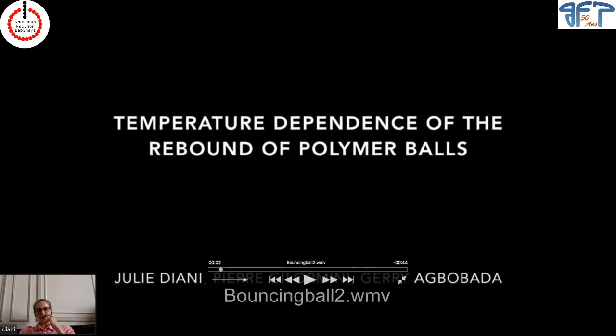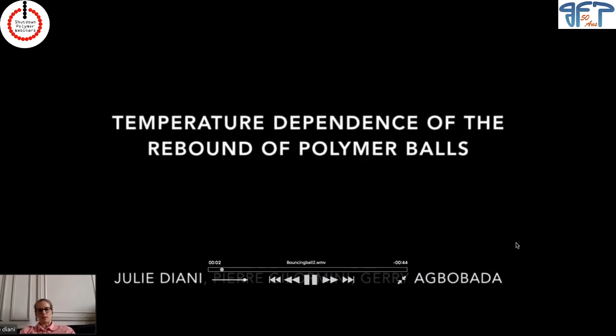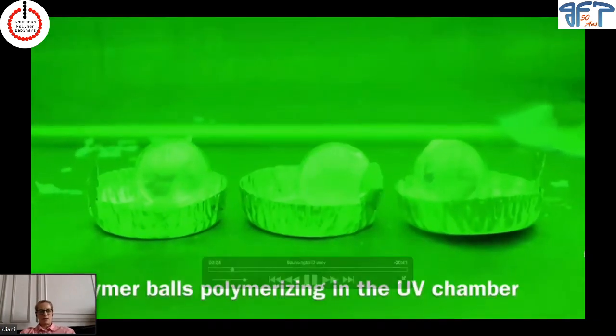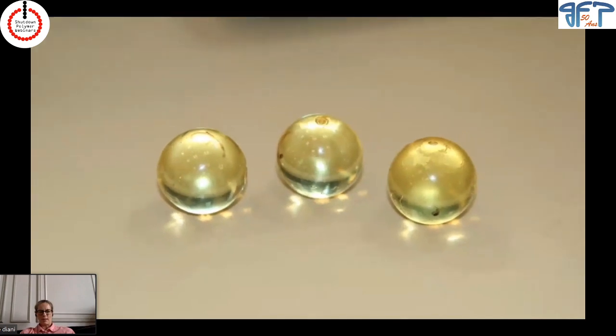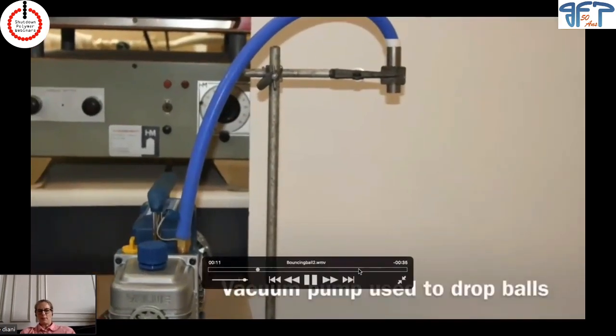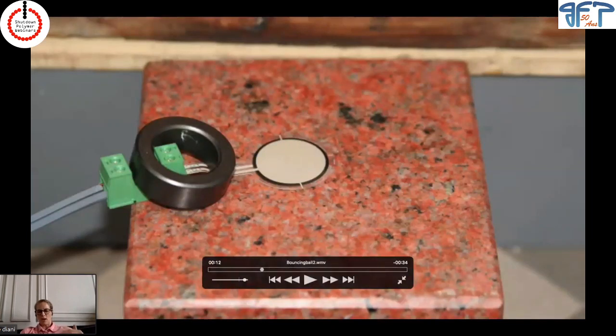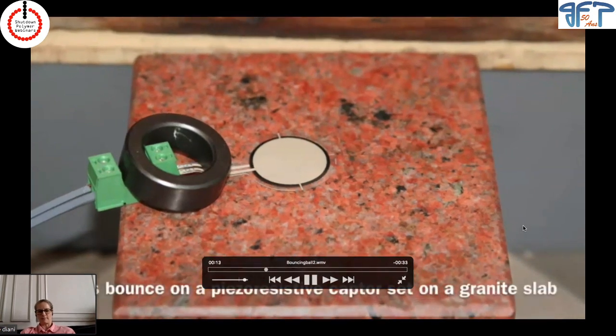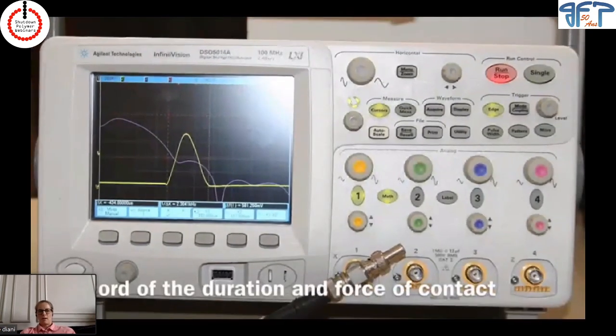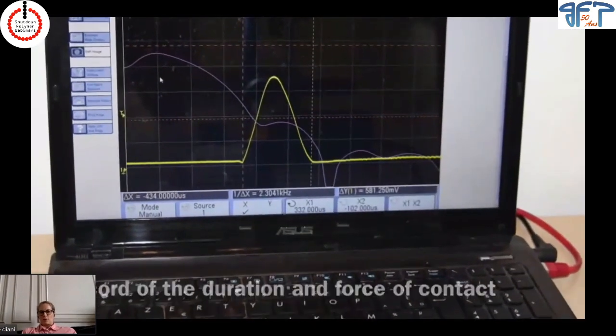So here is the experiment that the student ran at different temperatures. We're going to look at the rebound of the polymer ball. So after curing our balls, we had a pump to drop the ball straight onto a granite slab, and we put a piezoresistive sensor to record the duration of impact on the slab. Okay, looking also at the force of contact.